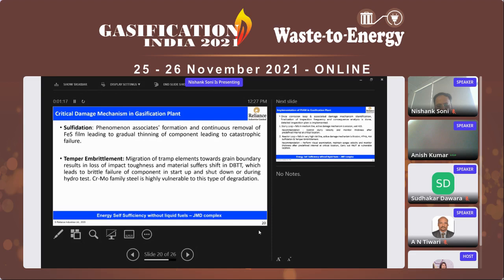This is a migration of tramp elements towards the grain boundary at the microstructure level, which ultimately results in loss of impact toughness, and the material suffers a shift in the ductile to brittle transition, which ultimately leads to brittle fracture. And this only happens during the startup or shutdown of any system. Chromium and moly family steel is highly prone to this type of degradation.